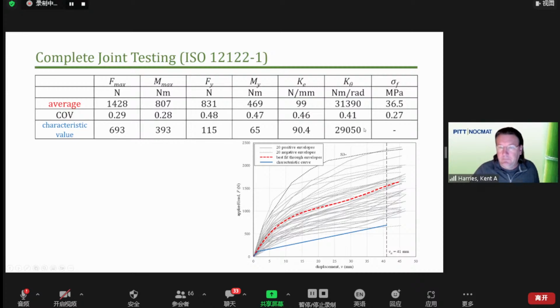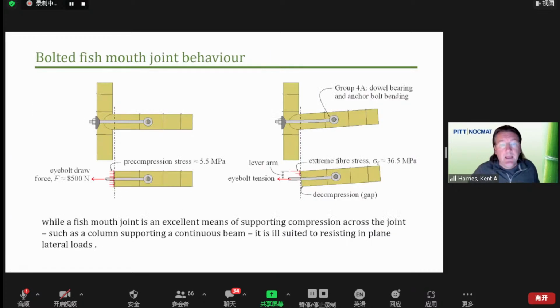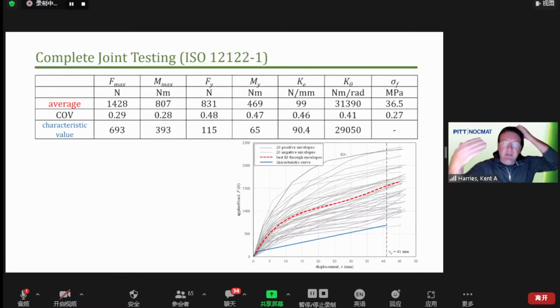Now this data, as we show here, here's all 40 curves, huge scatter, as we might expect from this type of connection. It's really not a moment connection. The red line is a best fit through all of the envelopes, so an average curve if you wish. The blue line in this case would be our characteristic value, assuming that we're using our 5% at 75% confidence. And so a very, very low bound, very, very poor moment capacity for this connection, which is probably what we would expect. And so that's the methodology that we would do for complete joint testing.